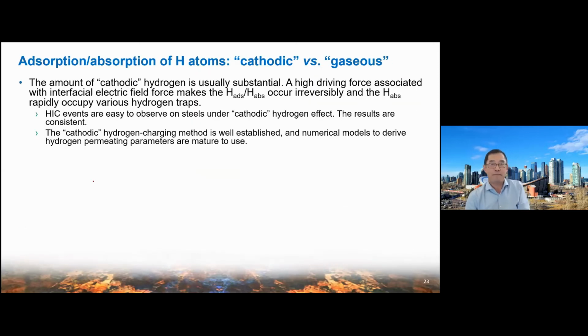After hydrogen is generated by the second mechanism, next it will go into the steel from the outside surface to the inside. This process I just mentioned also depends on the environment. If it is cathodic hydrogen, meaning hydrogen produced from the solution phase, this kind of hydrogen usually has a high driving force, because cathodic hydrogen is produced by the cathodic reaction. The concentration of hydrogen is usually much higher than for gas phase hydrogen. The driving force is much more significant, which can make the hydrogen quickly go into the steel and take all the potential sites for hydrogen accumulation.